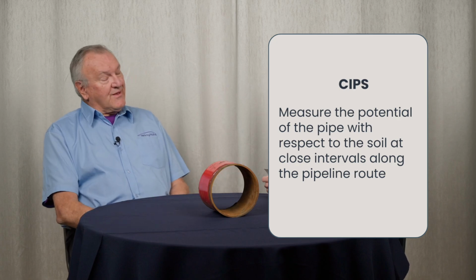Along the pipeline route. And typically that interval will be something close to the depth of cover of the pipeline. So if the pipeline is buried a meter and a half deep, then you take measurements literally at 1 meter spaces. And that tells you what the potential of the pipeline is.